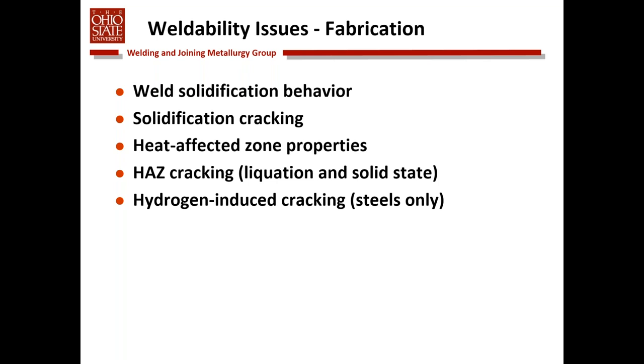We also need to deal with what happens in the heat affected zone. So when you make a fusion weld on a material or even a solid state weld, you normally heat the area or the material surrounding the weld to very high temperatures. This also causes changes in properties relative to those of the base metal. And we find that a lot of problems in some of our structural materials are associated with the heat affected zone, where we do not have the opportunity, as we do in the weld metal, to change the composition by adding a filler metal. So the heat affected zone often becomes a weak link in a welded structure. There are certain cracking mechanisms associated with the heat affected zone, liquation cracking and solid state cracking mechanisms. I'll discuss a couple of those today.